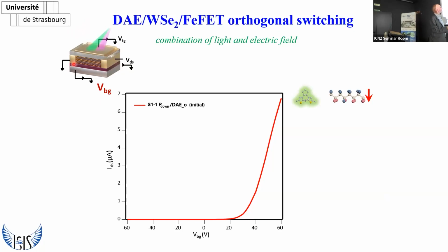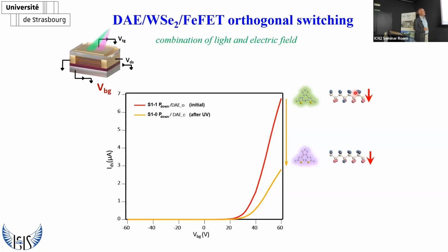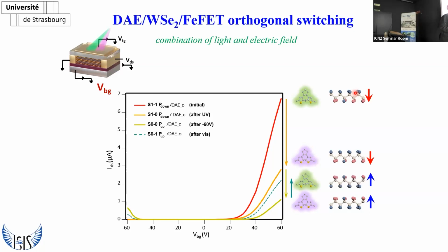Essentially, we start from the diarylethene in the open state, where we have, let's say, no trapping and all the dipoles pointing down, so higher current. Then we irradiate with UV light, we close the diarylethene, and we lower the current through the junction, with the dipoles still pointing down. Then we apply minus 60 volts, such that we swap the orientation of the dipoles of the ferroelectric molecule, and we have the lowest current possible. Then we irradiate with visible light, we reopen the diarylethene, then we apply 60 volts, and we go back to the initial state with the highest current possible.